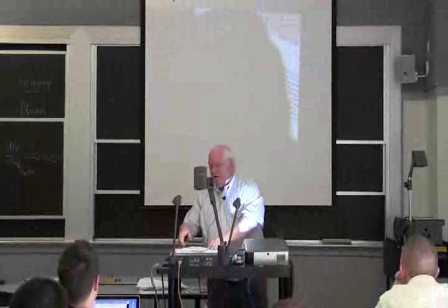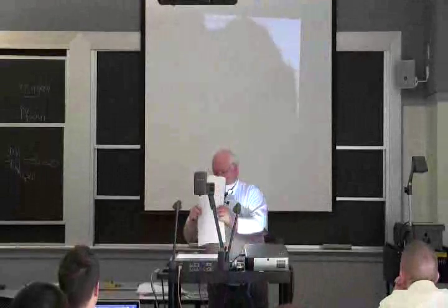And if you have a sharper angle, a very shallow angle, you can get very homogeneous straining. Depending on your angle and your lubrication, if you get too much strain at the surface, that's where the cracks start, at the surface. And so if you initiate a crack, you're done. You probably try to put in another die, it's already got a crack there, then fracture mechanics tells you it's just not going to work.